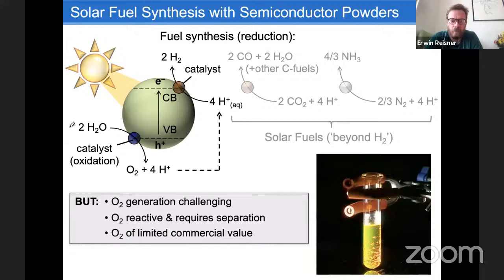But I still think there are quite some niches, or maybe even larger than niches, where we can start thinking about replacing this water oxidation to oxygen. But before I come to this, maybe just a few limitations of water oxidation. Water oxidation making oxygen is actually a quite challenging catalytic process. Oxygen generation is challenging from a catalytic point of view, simply because you need to move 4 protons and 4 electrons, but also from a thermodynamic point of view. So this 1.23 eV I mentioned before is mostly so endothermic because water oxidation is so demanding.